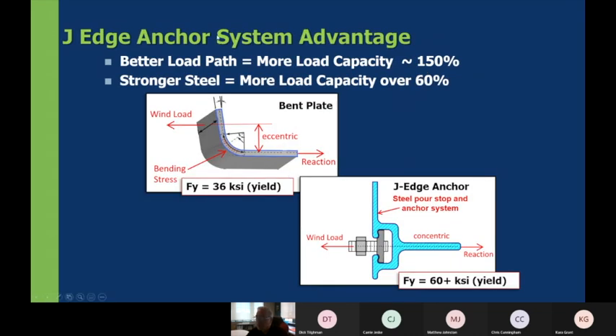So some of the system advantages we'll start getting into now for J-Edge Anchor System. One of the great benefits that we see associated with J-Edge is it's much stronger. It has more load capacity than the standard bent plate at the slab edge. Part of that is due to a better load path because we have a reduction in eccentricity. So the typical wind load or connections would be welded on to the upper parts of this bent plate, and that induces a bending stress down around the bend due to the eccentricity of the load. For J-Edge Anchor System, it is a concentric reaction that we have. It gets rid of all of the bending stresses associated with it.